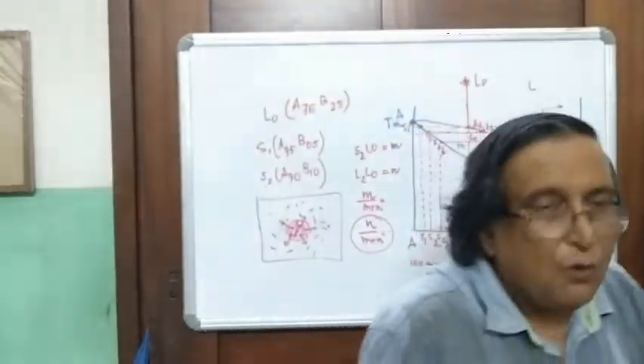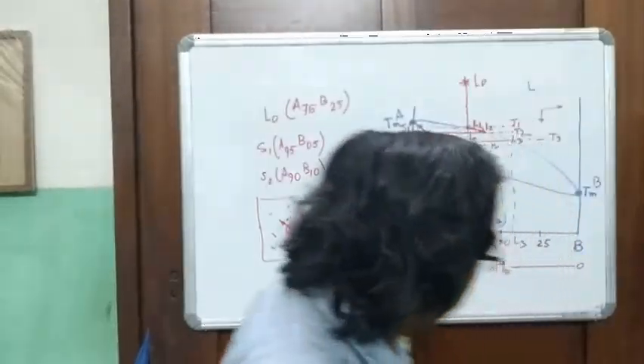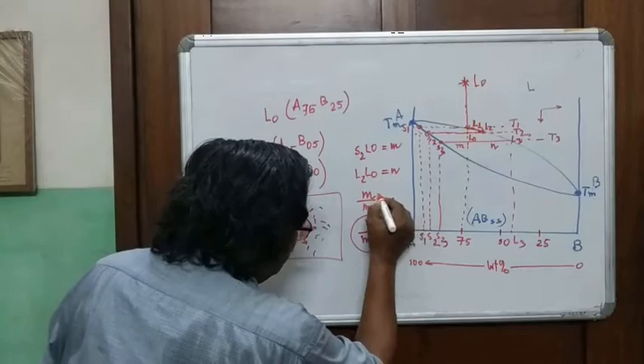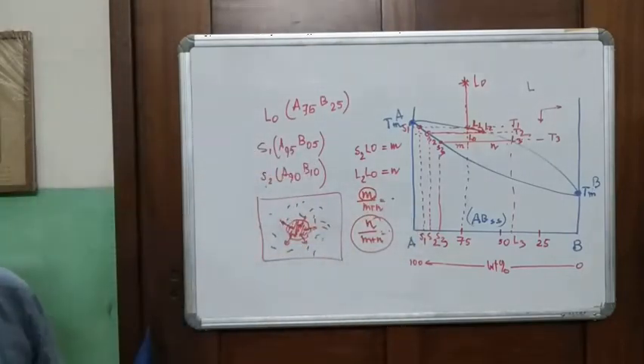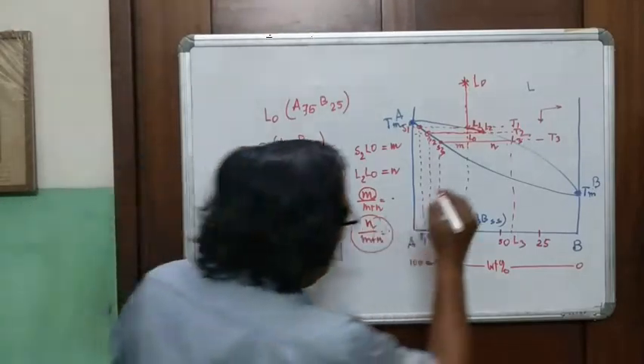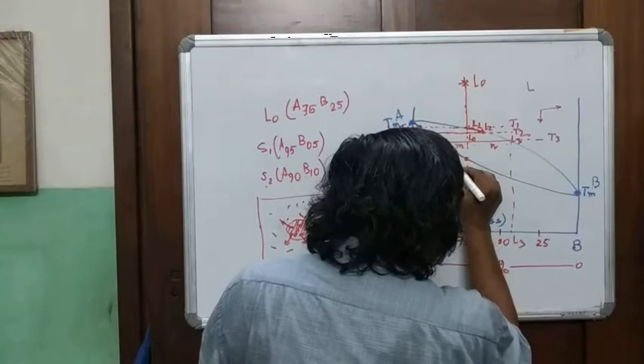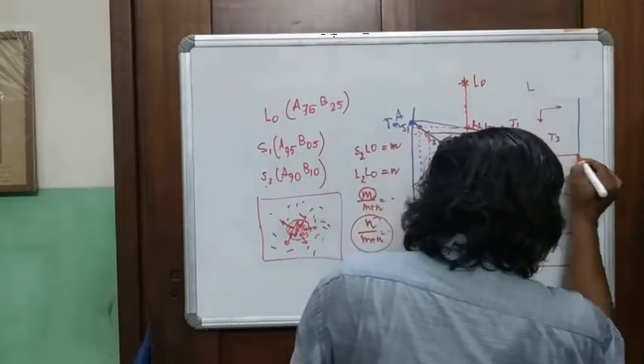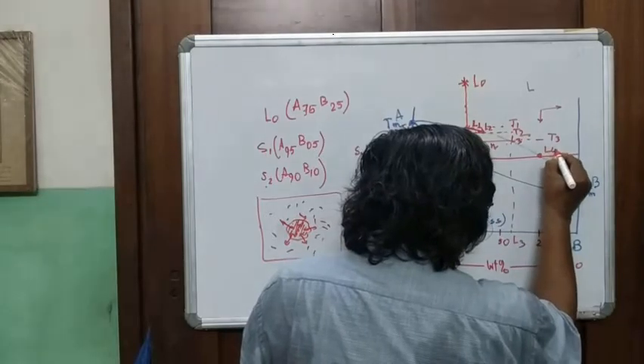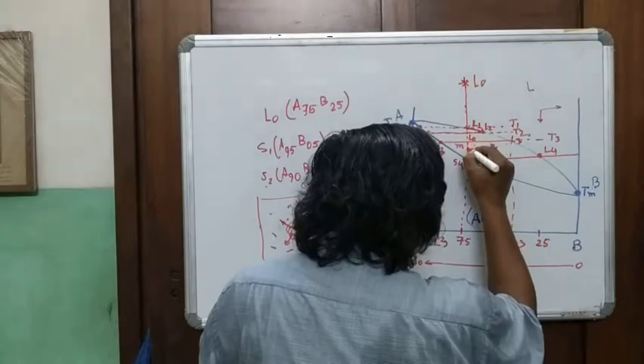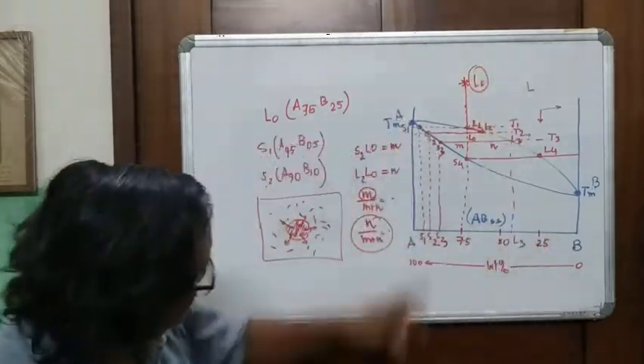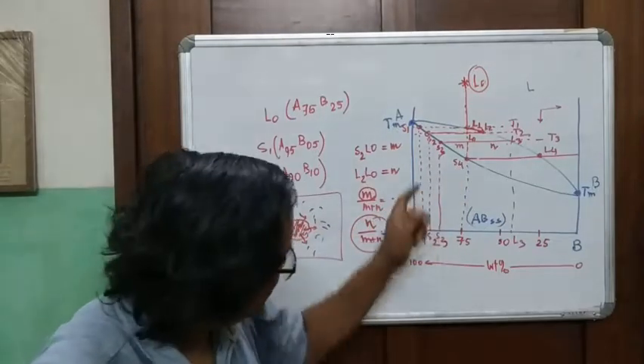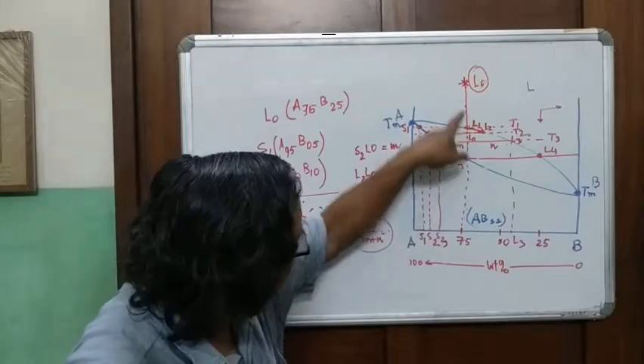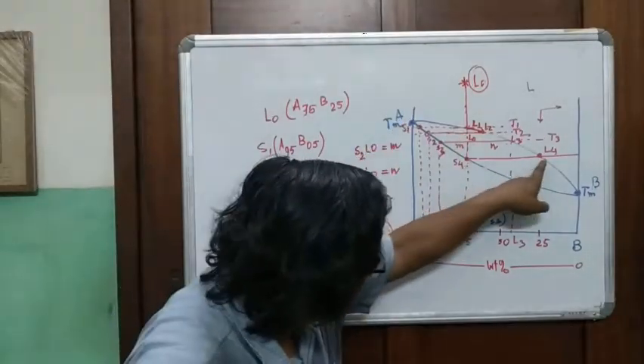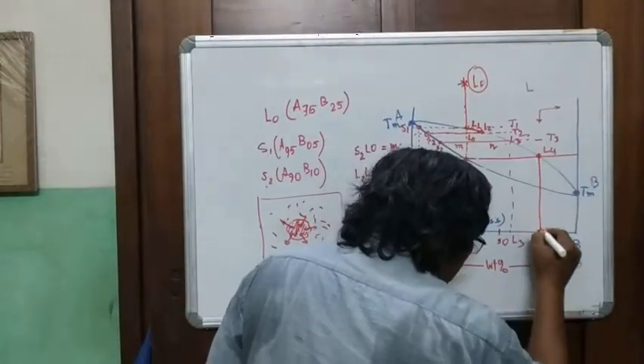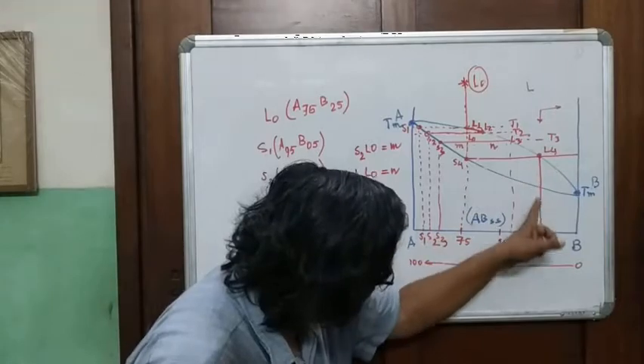Now, when will this event stop? As you can see, if this is the fraction of melt, then M will become equal to 0. Where will M become equal to 0? When this S3 point will reach here. Can you see this? This is where you will have L4, and this is where you will have S4, and this is the point where it was L0. So when the composition of the solid along the solidus coincides with the initial composition, this will be the new composition of the melt.